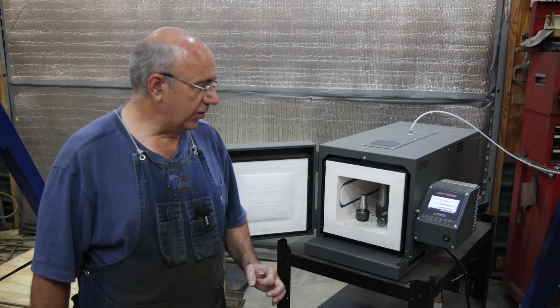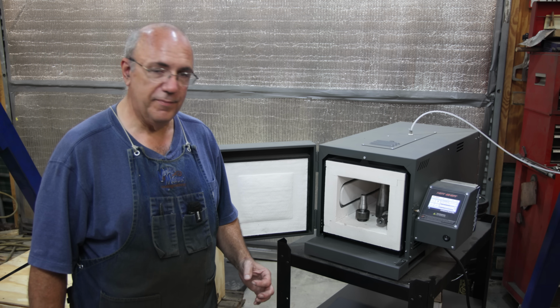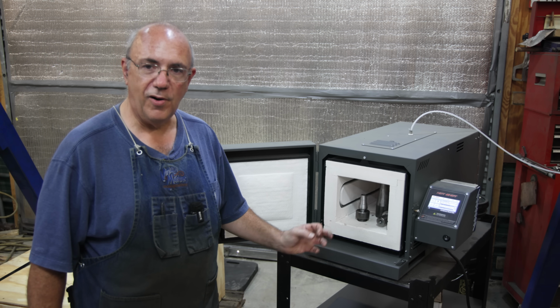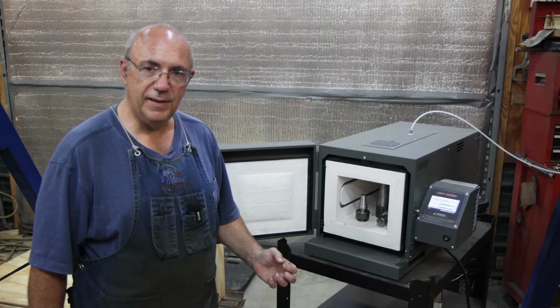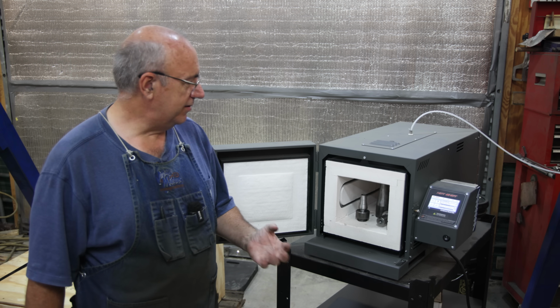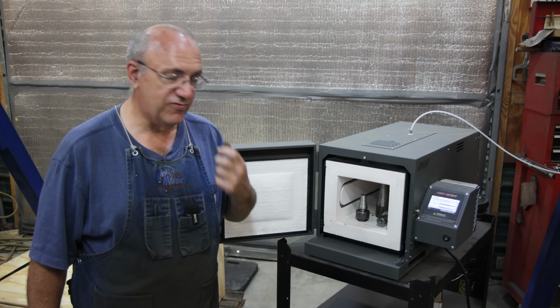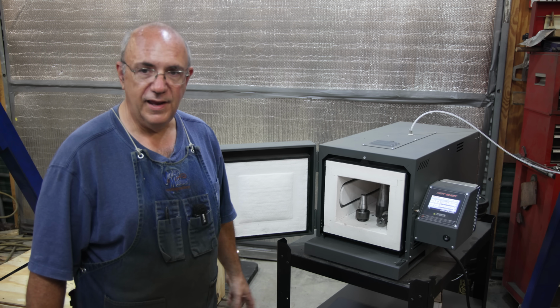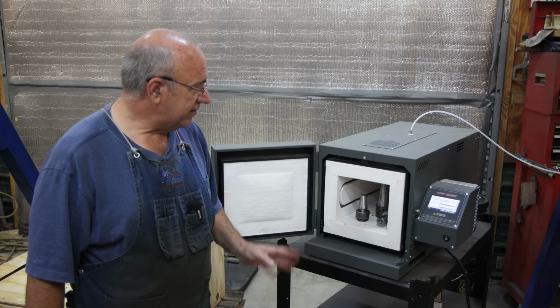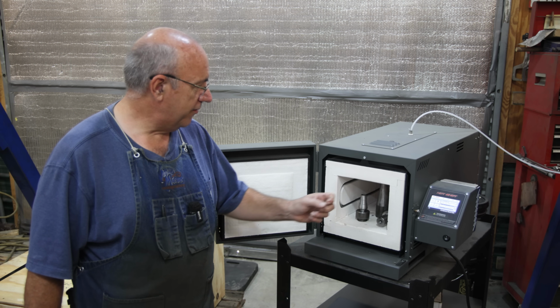The oil will cool them down and harden them. After that, we'll go through a tempering process to actually soften them back up a little bit. And if I remember right, we'll basically put it in there at 600 degrees Fahrenheit for about 45 minutes and then let them air cool. That's kind of the process. I've got it programmed here ready to go.